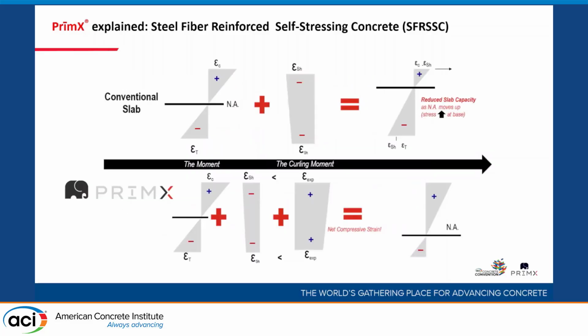The other, of course, is the structural part. So you have a typical situation of a slab on ground or any kind of slab, and you put it in flexion. So typically you have the tensile on the bottom, and then there's a compression zone on the top. And if you add shrinkage to that, it's going to shift the natural axis of your slab upwards. But if you can add this expansion part, and as I said, typically it's a bit more on the top because it's better moist curing there, then you can actually shift the natural axis downward, and by this principle you can also optimize the structural design part and reduce the slab thickness, which is a big driver for the embodied carbon.